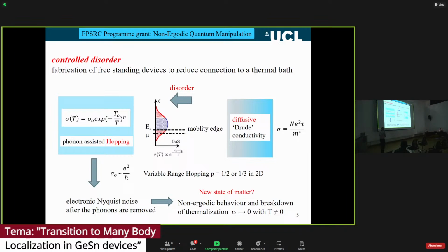Now, the interesting fact here is that we can change the chemical potential with gating, so we can use a gate to change that chemical potential. We can change this energy between the chemical potential and the mobility edge. And if you measure the conductivity in the system, the conductivity is thermally activated. It's a simple exponential, and the characteristic energy is the energy between the chemical potential and the mobility edge.